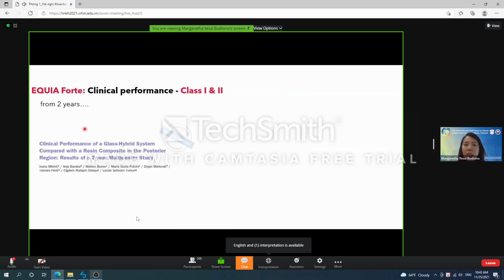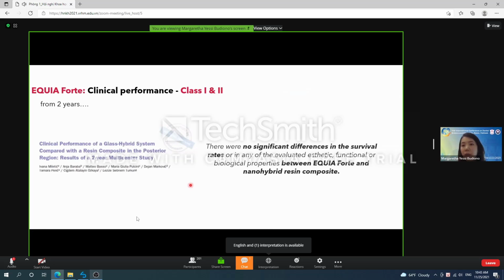So for example, this one, the strength of EQUIA Forte HD. This is a 2 years study on clinical performance between EQUIA Forte and nanohybrid resin composite in class 1 restoration. And it was found out that there were no significant differences in the survival rates between EQUIA Forte restoration and composite restoration. And even for class 2 restorations, where many conventional GICs fail, it was proven that there is no significant differences between glass hybrid and resin composite. And in fact, EQUIA Forte can be considered as permanent restorative materials for large class 2 cavities.